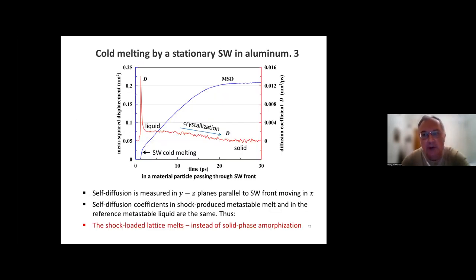And finally, as I promised, I show the evolution of the mean square displacement of atoms, and as a derivative, its slope, the self-diffusion coefficient. So you see clearly that at the shock front, the displacement of atoms sharply increases, and it is associated with a very huge peak of the self-diffusion. Then we have a relatively large slope in the liquid, so normal self-diffusion in the liquid state, which is just the same as in a reference system. And then during crystallization of this metastable liquid, you can see that the mean square displacement goes to a plateau with almost zero slope. It means the self-diffusion coefficient in the solid is near zero.